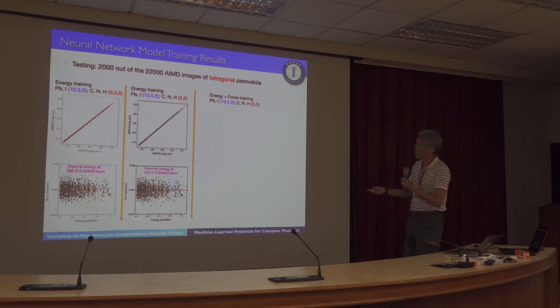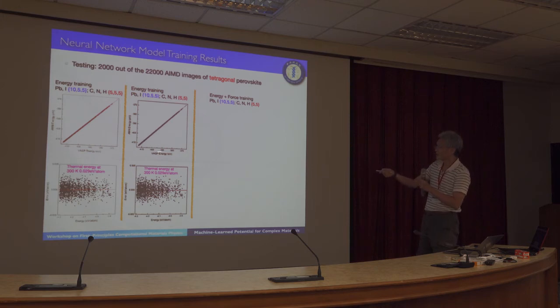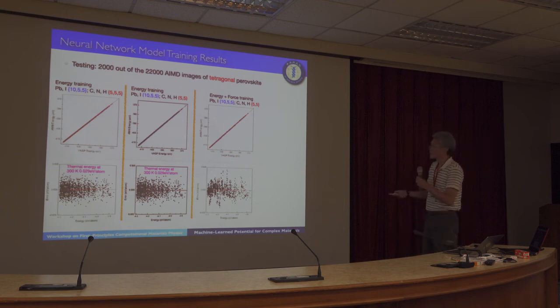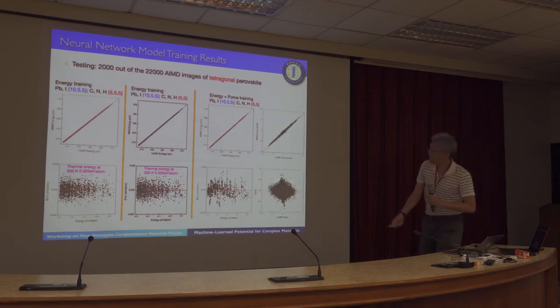And for setting 2, once again, it's also in very good agreement with that from VASP. And for setting 3, just looking at the energy, also in good agreement. And if we look at the force, once again, even for atomic force, this is the force from VASP, and the force predicted from the neural network model, also in very good agreement.